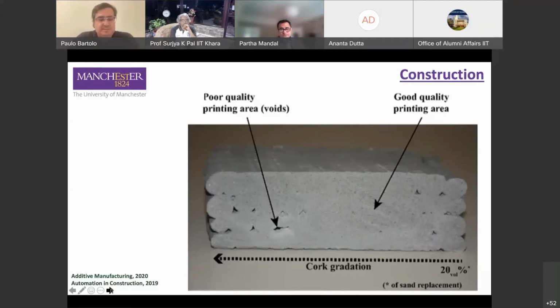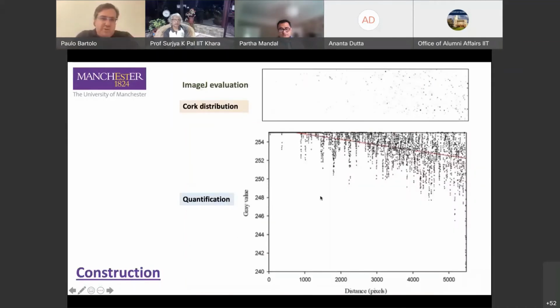concrete system. Besides reducing the weight of the construction element and reducing the amount of concrete with significant positive environmental impact, this strategy will allow us also to create houses with much better thermal performance. So this image shows that effectively we were able to have a good control over the amount of cork during the printing process.